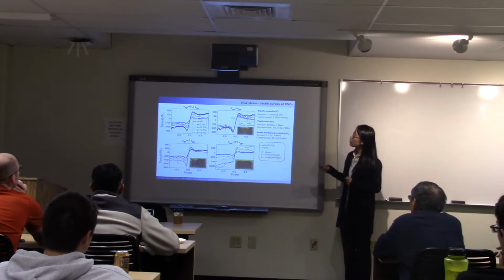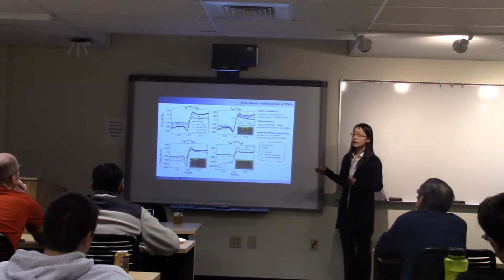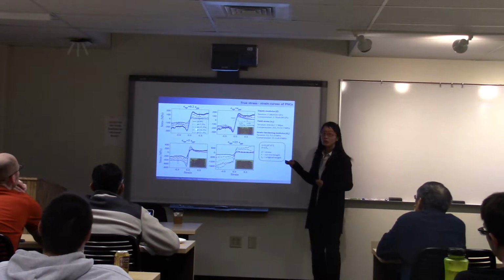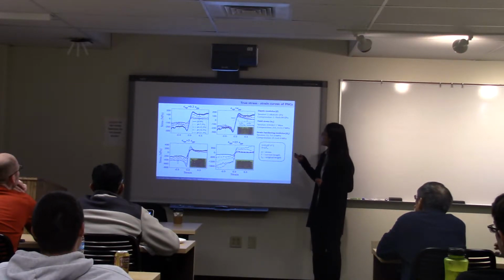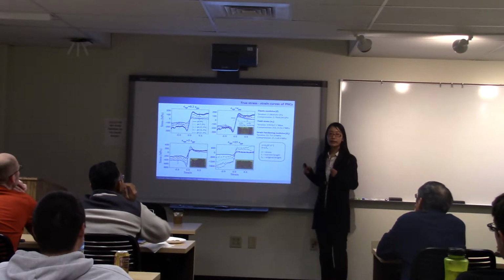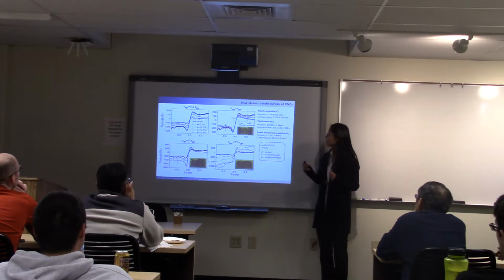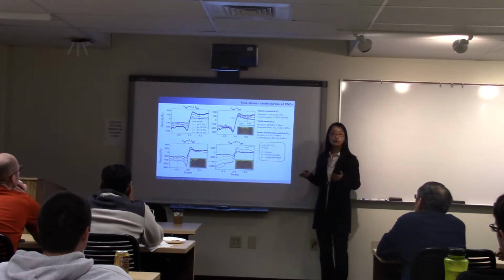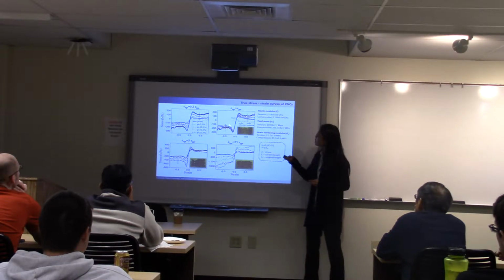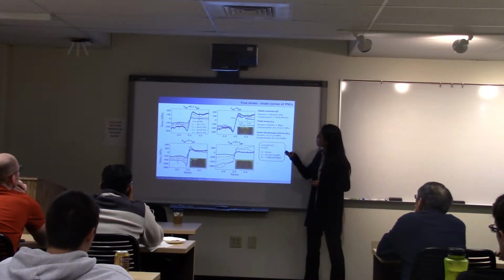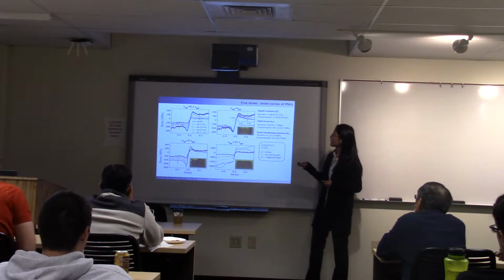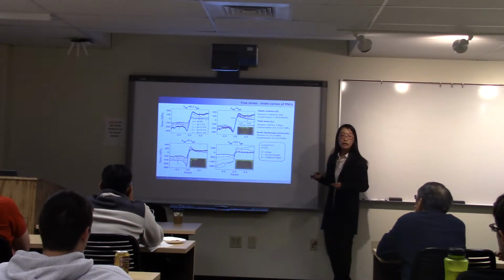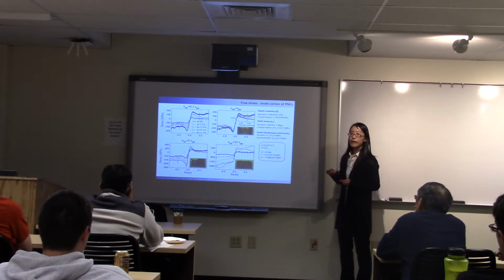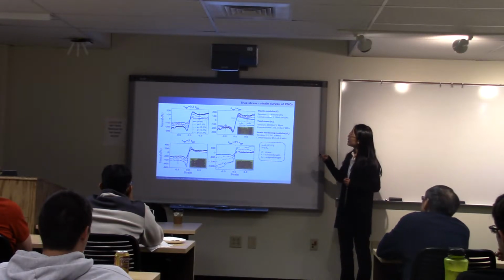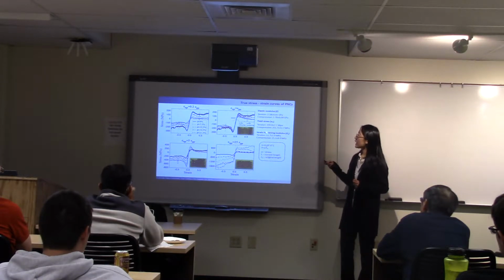Now here I show some true stress-strain curves of the polymer nanocomposites. First let us look at this black line, which is the polymer response without any nanoparticle loading. It shows the typical response of a polymeric system: the elastic region, strain softening, as well as strain hardening. We can extract some important mechanical parameters from this curve, such as the elastic modulus, the yield stress, as well as the strain hardening modulus.